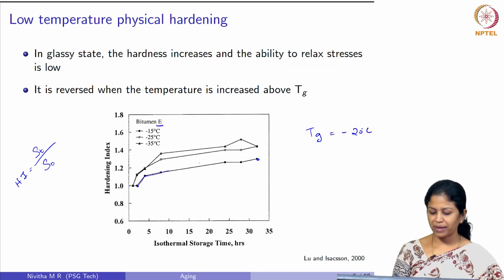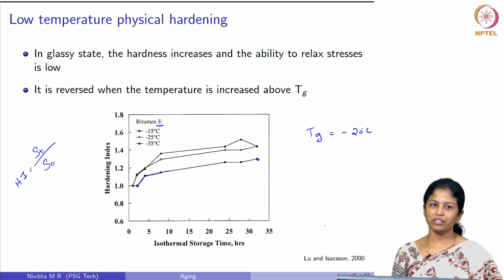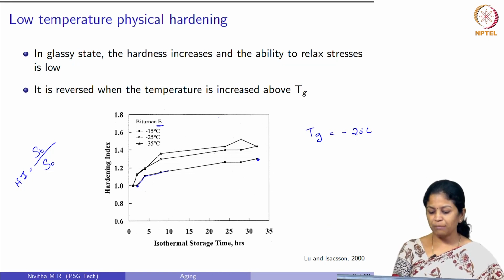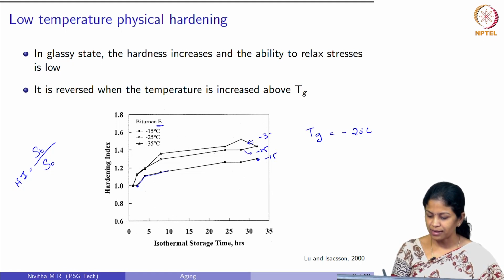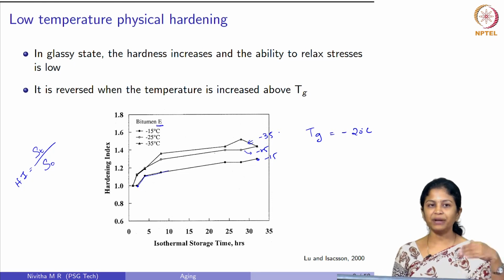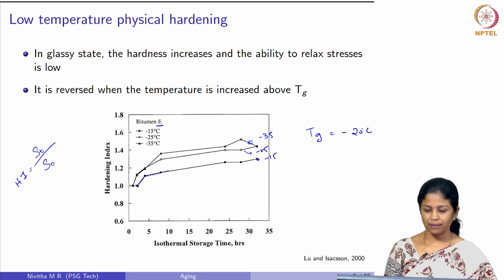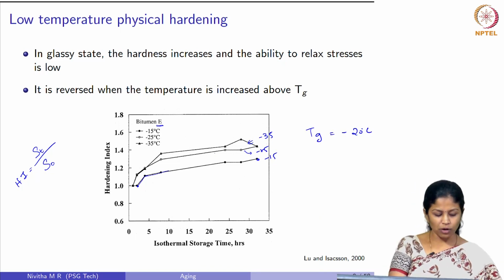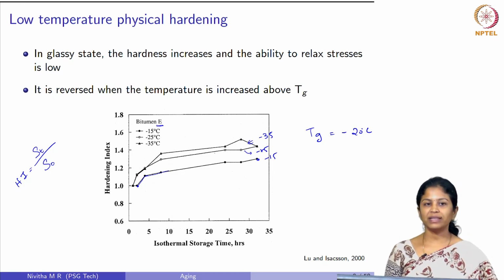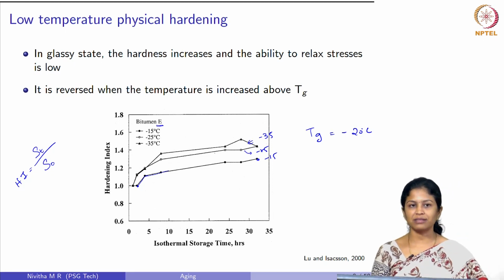We can see similar behavior for -25 and -35 degrees Celsius. We can also see as we go lower and lower in temperature, the hardening index keeps increasing. So, this is for -15, this one is for -25 and this one is for -35. So, this is the phenomenon of low temperature physical hardening, and this phenomenon is reversed when the temperature is increased up above the glass transition temperature.